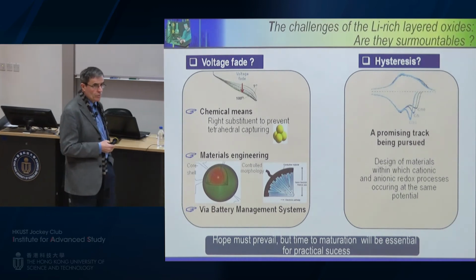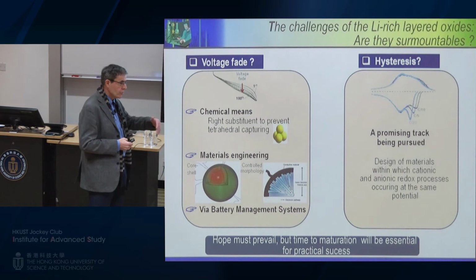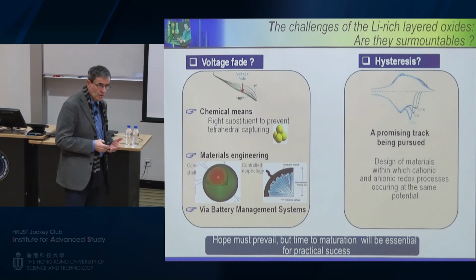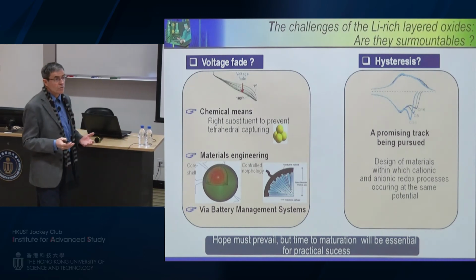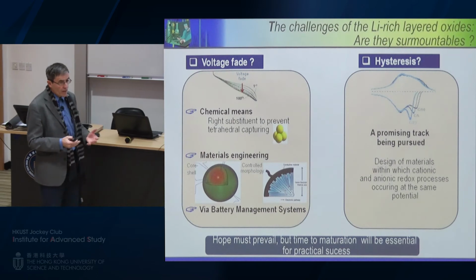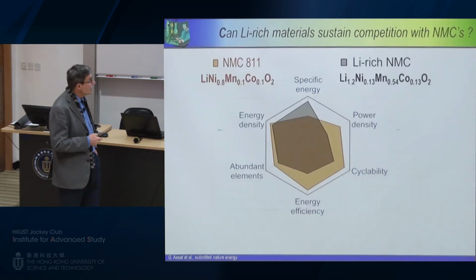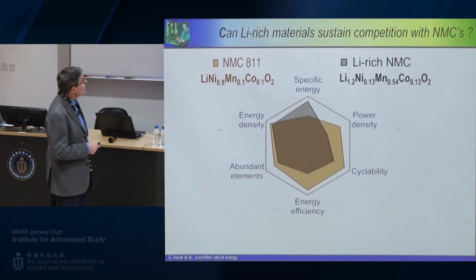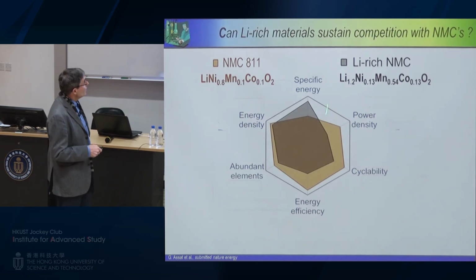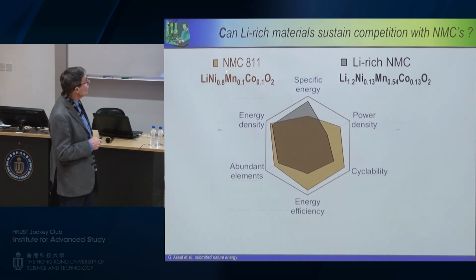And I think we are going to see that when people started this research 5 years ago, a large amount of hope was placed into the materials. And with time, as you can see on this slide, where I compare in this spider plot the lithium NMC, where people have been moving from 532 to 811, this compound indicated here, and the lithium-rich NMC.